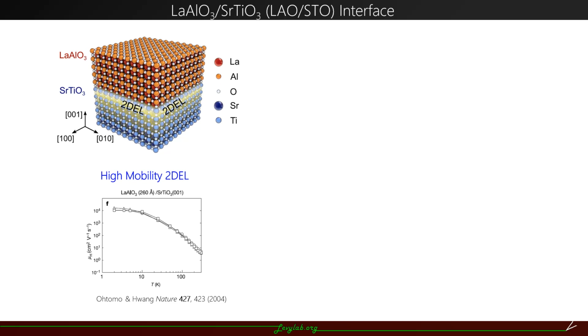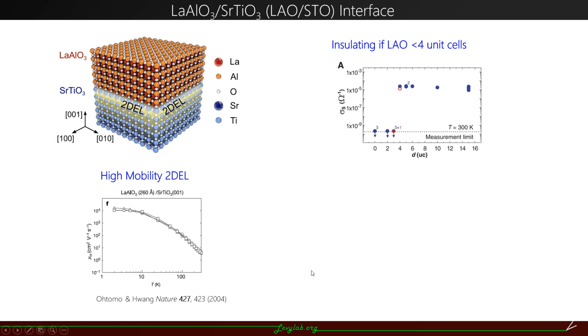Individually, both oxides are insulators. However, when they are put together, the interface becomes electrically conductive with very high electron mobility. One interesting property of this interface is that it has a critical thickness of 4 unit cells for the LAO. This interface will be conductive only if the LAO thickness is more than 4 unit cells.